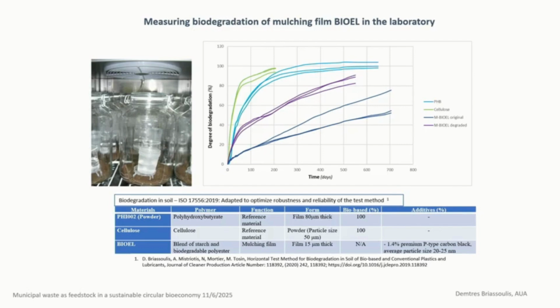Why did we do that? Because we simulated the natural degradation of the film in the field exposed to the sun's UV radiation. And without artificial aging is the lowest curve, which shows a slower initial rate of biodegradation. Within a period of 1.5 years, this film is biodegraded. The standard specification requires more than 90% biodegradation within a period of 2 years.